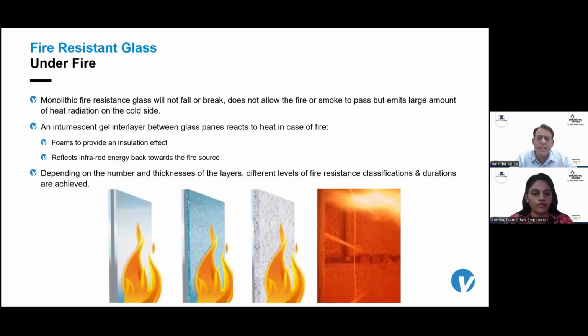So on the fire side, if we have 600 degrees Celsius, the non-fire side will eventually go to again 400 plus, 500 plus within a very short period of time. That is again within less than 10 minutes, it will go to that high a temperature. That means I cannot cross that area, because I will die if that side is even more than 100 degrees Celsius.